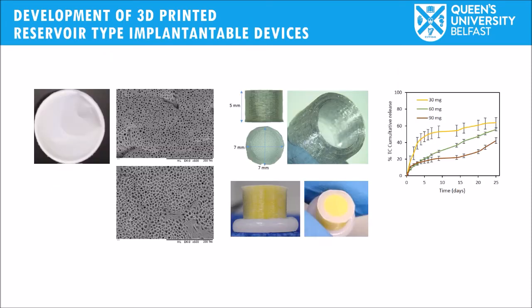In addition to those types of implants, we finally developed other applications of these rate controlling films and FDM 3D printing. In this case, we created a new type of film that was not made of polycaprolactone. Polycaprolactone has a low melting point of around 55 degrees Celsius. As soon as you try to print around those membranes with materials such as PLA, which has a melting point of around 180 degrees, it will be melted. So we decided to create PLA-based membranes, and in order to be useful for drug delivery, as you can see here, highly porous membranes by combining PLA with low molecular weight polycaprolactone.